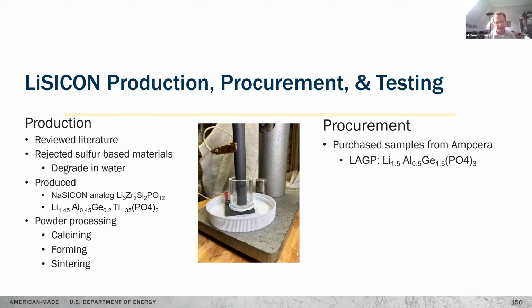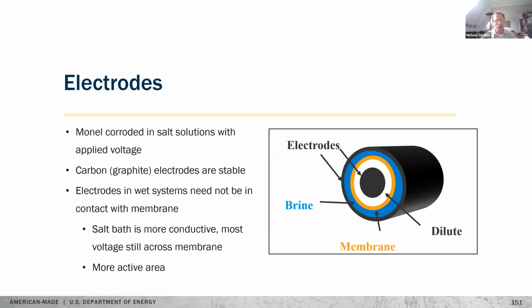We put distilled water on top, applied a voltage, recorded a flowing current, and then we analyzed the distilled water for lithium and sodium. The lithium to sodium ratio flipped by over a factor of 3,000. So this is highly selective for lithium. We will continue testing with other components. Next slide, please. Electrode testing.